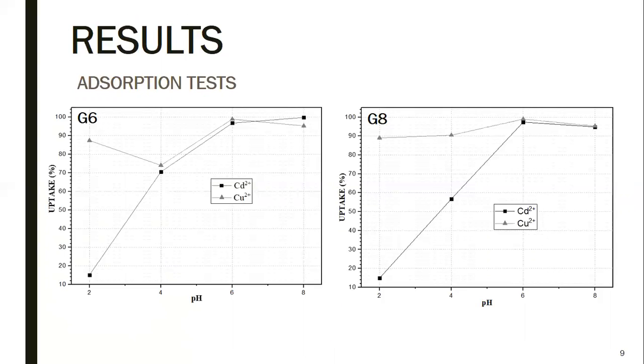Lastly, adsorption test graphs show the influence of pH on adsorption capacity. For cadmium and copper, the uptake increased when pH increased until a pH of 6. The best adsorption condition is at pH 6. At lower pH, the heavy metal isn't in ionized form, which affects the correct flow of the ions through the geopolymer pores. In both cases, the uptake reached over 90%, which indicates that geopolymer is a good option as an adsorbent of cadmium and copper. Thank you so much for your attention.